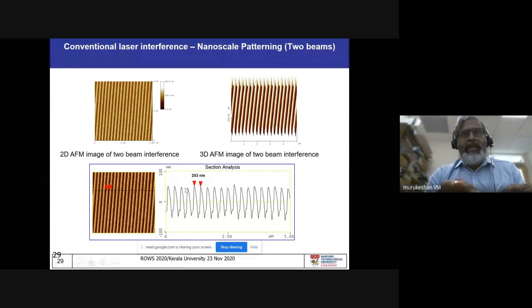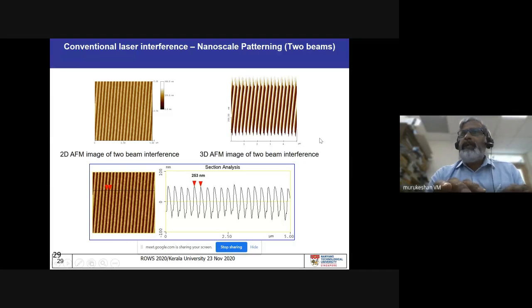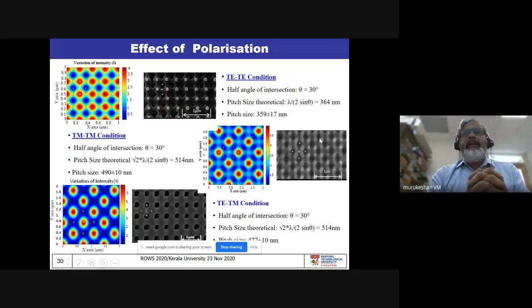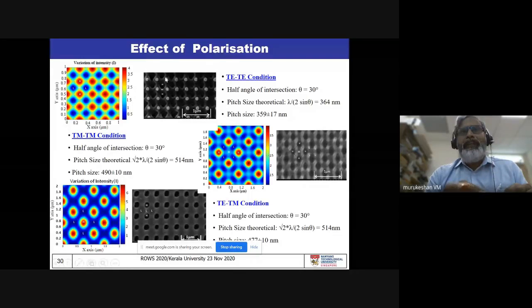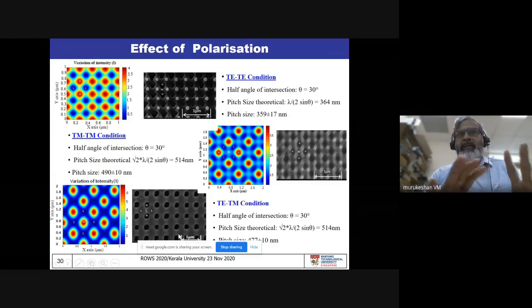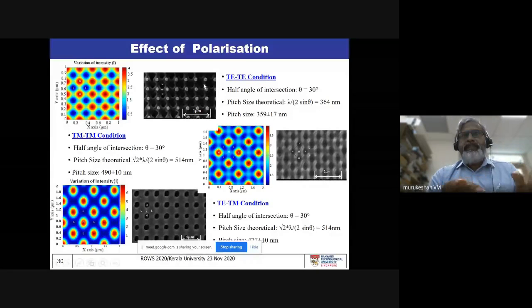And we tried to do a lot of analysis and see what we can do further. In between, we were trying a lot of physics optics work by changing the state of polarization between the counter-propagating beams. And you see that it follows exactly the theoretical simulation that you're doing there. And you can get very nice, interesting features that you can see here. But the only thing is that the pitch size is around 500 nanometers when we manipulate this state of polarization and other parameters. But this has very nice, very important applications in biosensing and other applications. So these are the kind of work you can do.